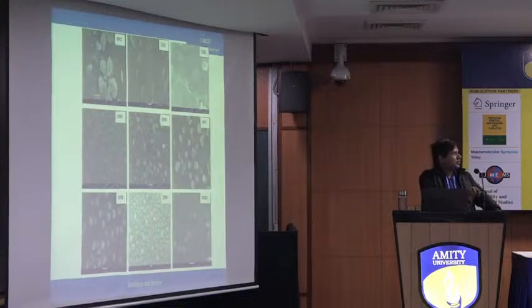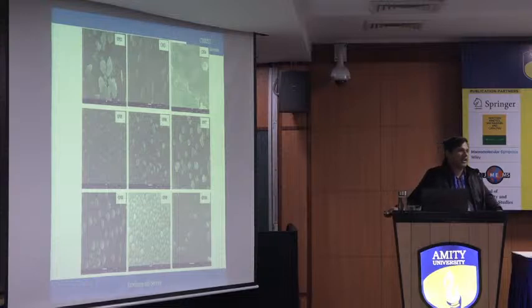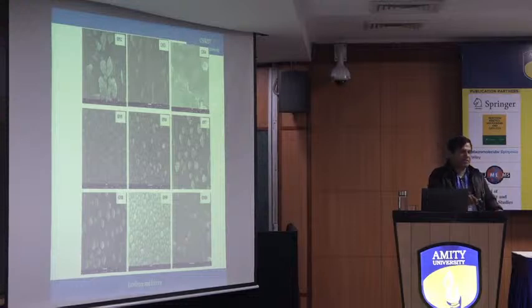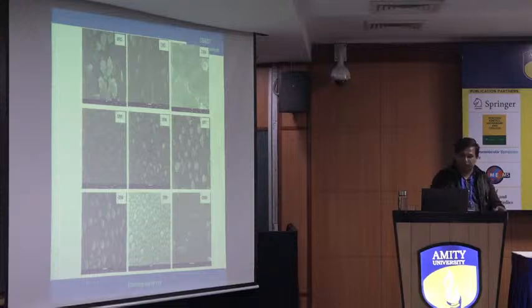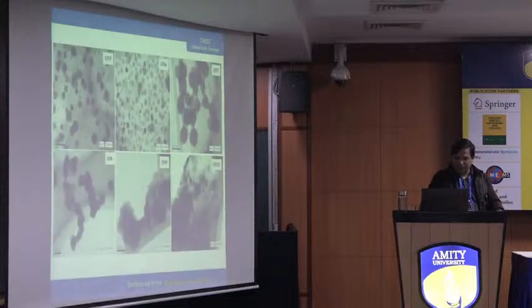The next one is we wanted to know where exactly this kind of porosity starts coming. We worked on onion-based nanoparticles. We took the onion peels, which is again funded by the Government of India, and we started heating the onion peels at different temperatures. You can see at 500 degrees onwards, a very nice spherical shape starts coming, and at 900, it's perfectly spherical. And again, TEM also proves the same thing.